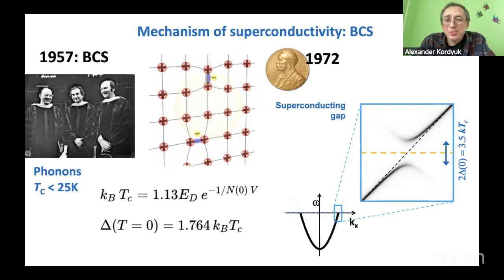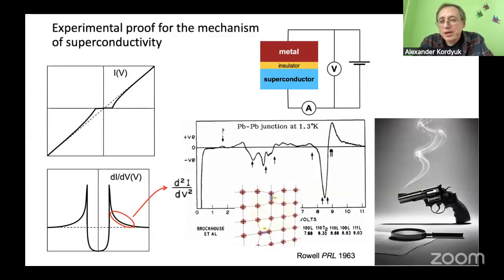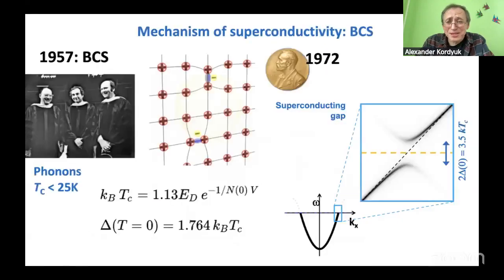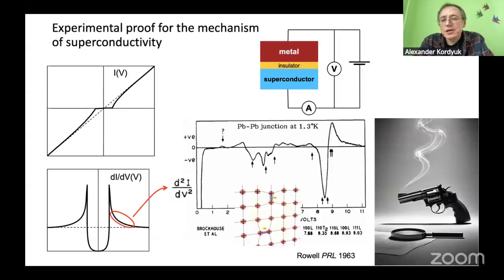And the model for this phenomenon was introduced in 1957, the so-called BCS theory, Bardeen-Cooper-Schrieffer. They suggested that electrons pair with the exchange of phonons, with the exchange of vibrations of the lattice. This mechanism explains the superconducting gap and many things which were observed, but it was accepted. I wanted to say that it was immediately accepted, but not. I found that actually the Nobel Prize was awarded not very fast after the discovery. My impression before was that just a few years passed, but it took some time in fact. But compared to high temperature superconductivity, it was probably fast.